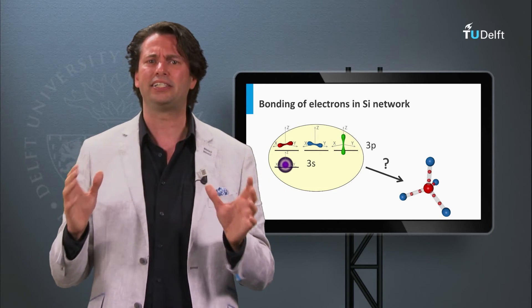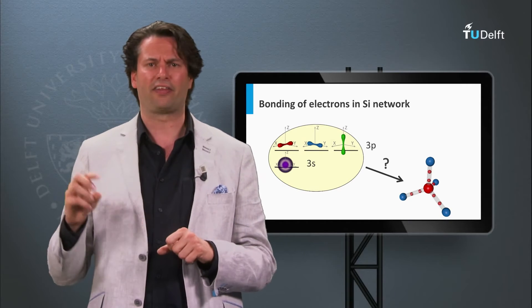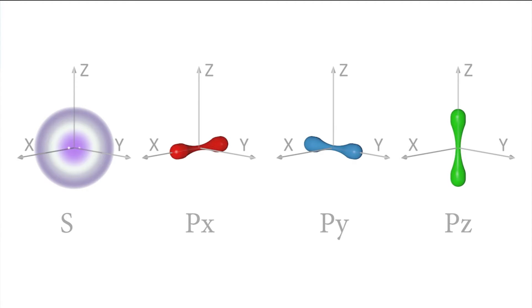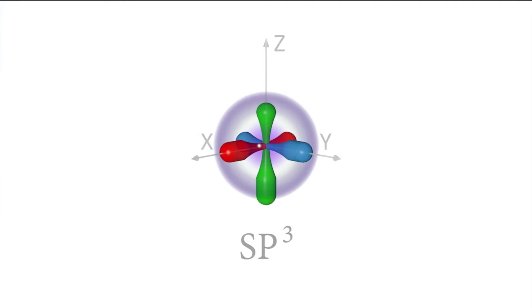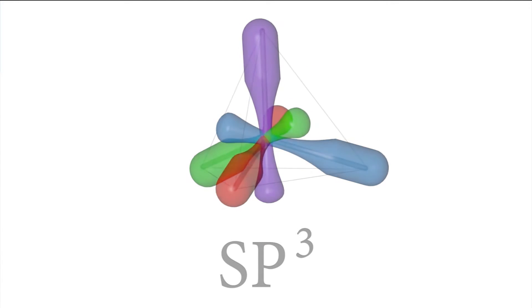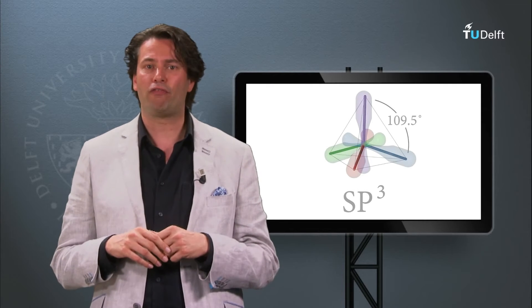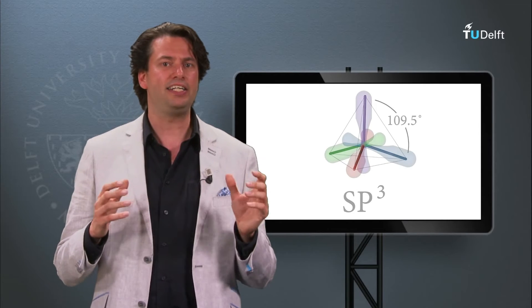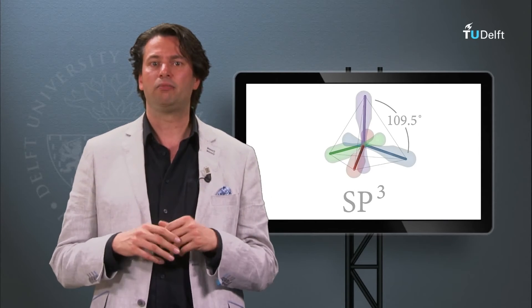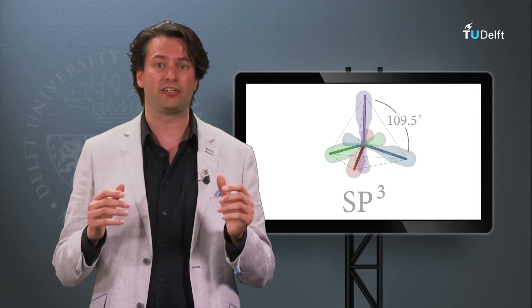How are these states related to the orbitals? To explain this, we consider one electron in the 3s state and three electrons in the 3p state. We now make a cocktail of orbitals — we mix these four states. In nature, it appears that these four states mix into effectively four symmetric states. The animation demonstrates the mixing. The four resulting symmetric states are called the sp3 hybrid. In nature, the four valence electrons behave as if they are in these four sp3 orbitals. The orientation between these four orbitals corresponds to the tetrahedral coordination with an angle of 109 degrees between them.